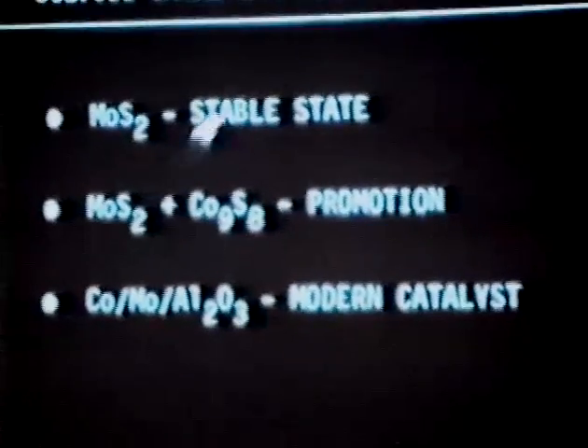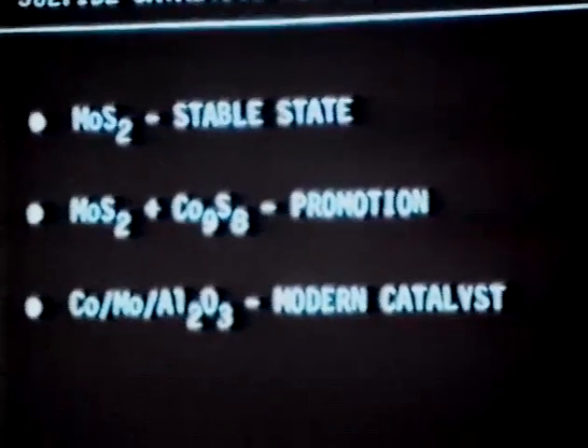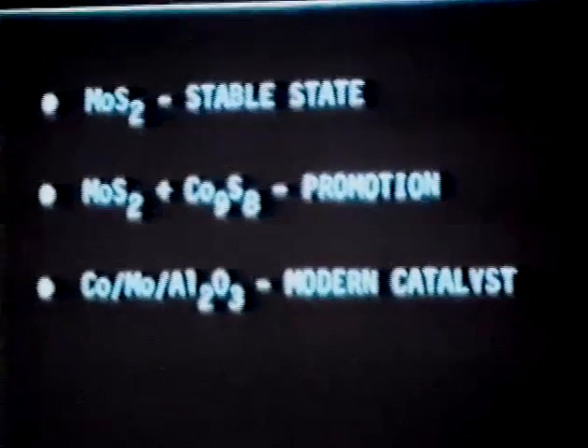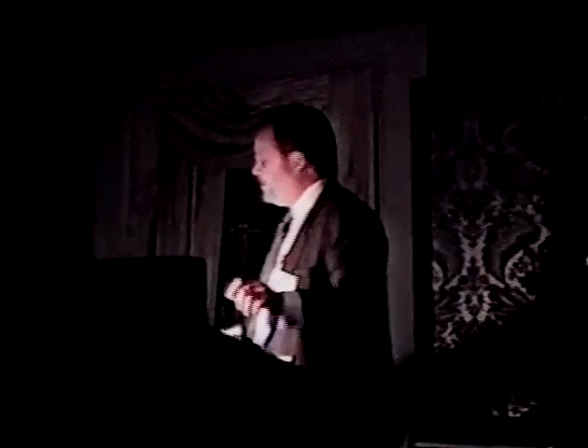The second point I'd like to make is that the promotion effect, which you're all familiar with, involves at least these two forms of stable states of the sulfides in the catalyst, and that the promotion effect can be completely described in terms of those stable states and their interactions. I say that because the catalyst that we all use is a cobalt molybdenum on alumina catalyst, and though we will have some controversy about this, you can think of the alumina as something that disperses the stable states of the catalyst and that can add other functions like acidity, as some of the talks will go through. But basically, the promotion effect is contained in these two phases here.